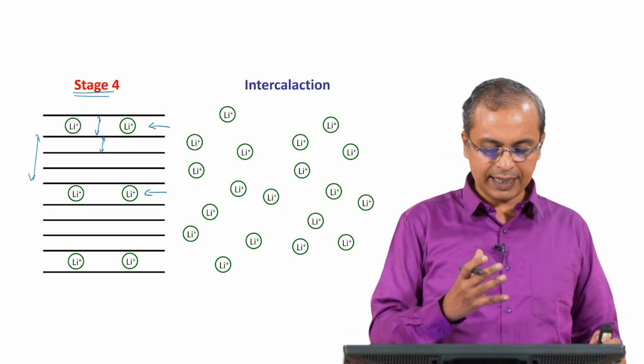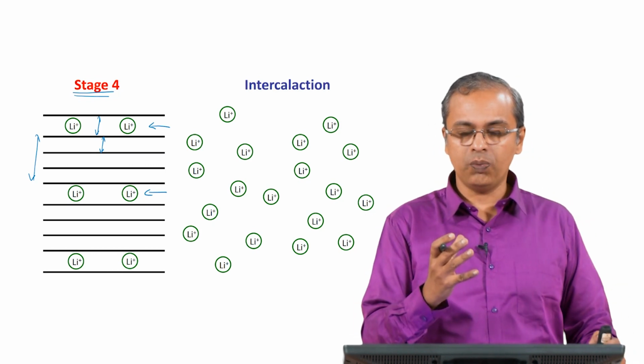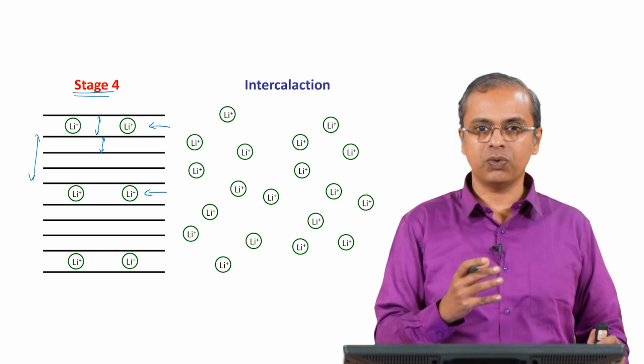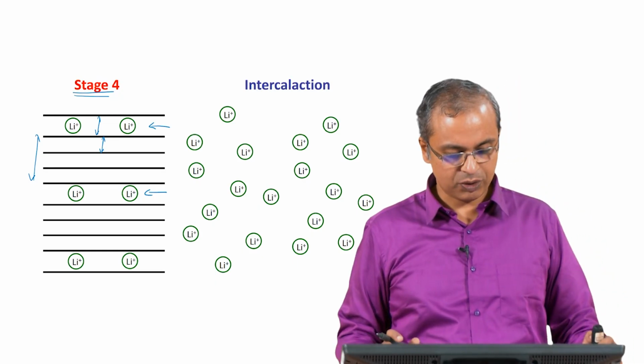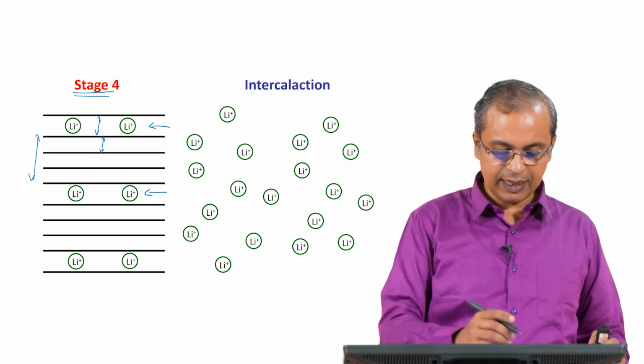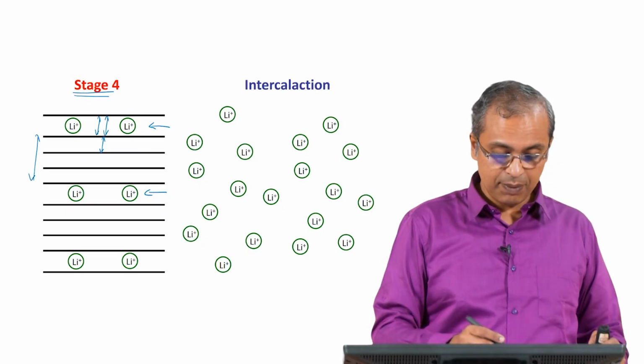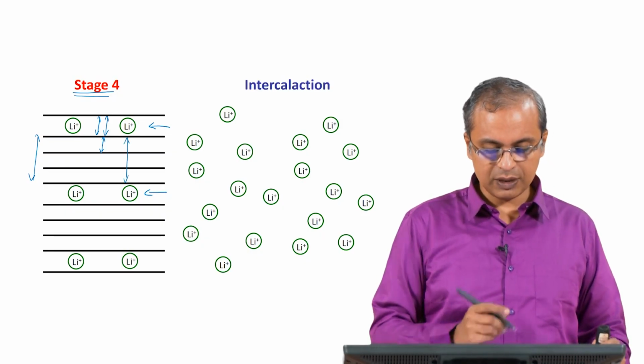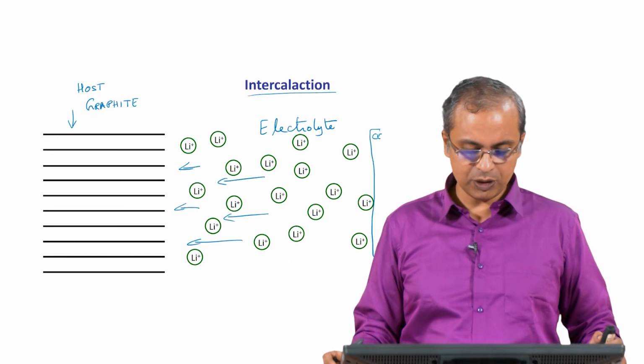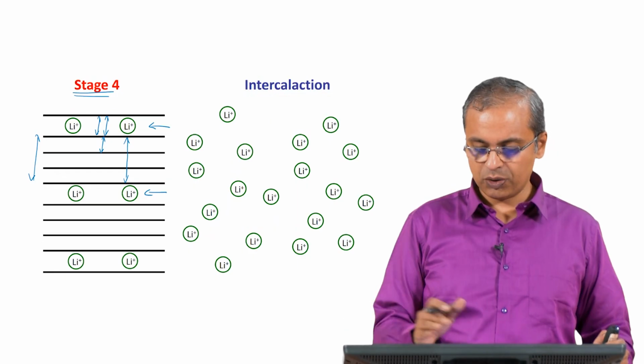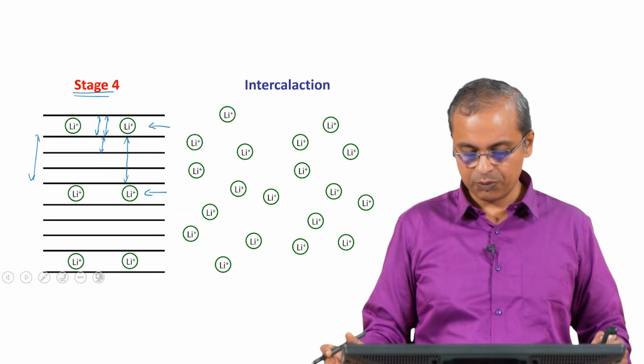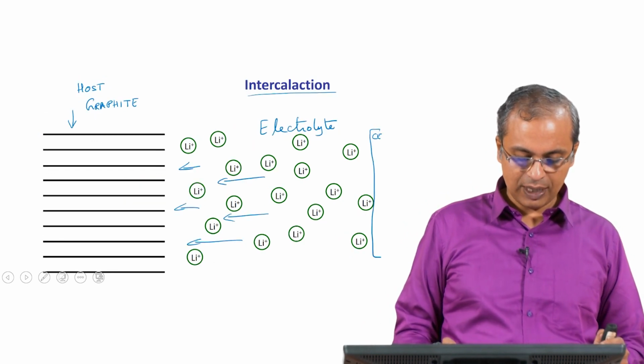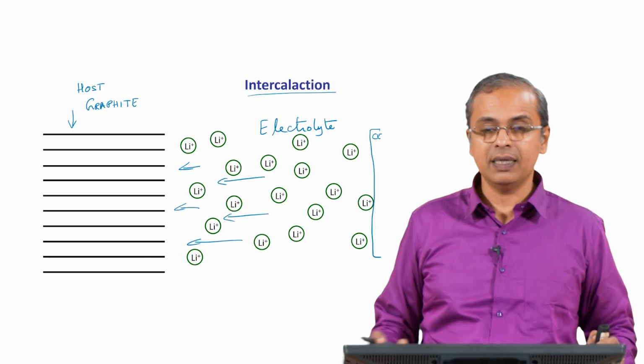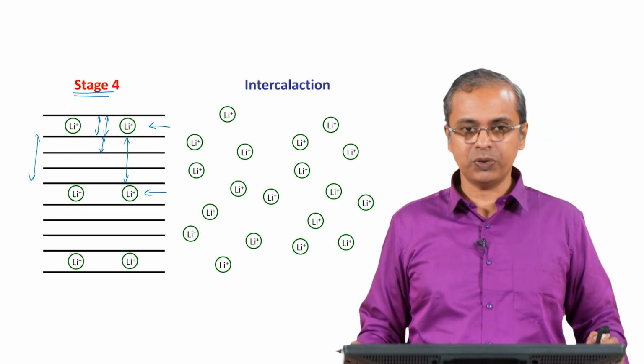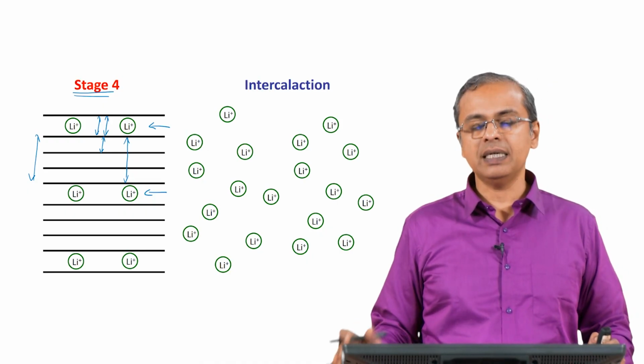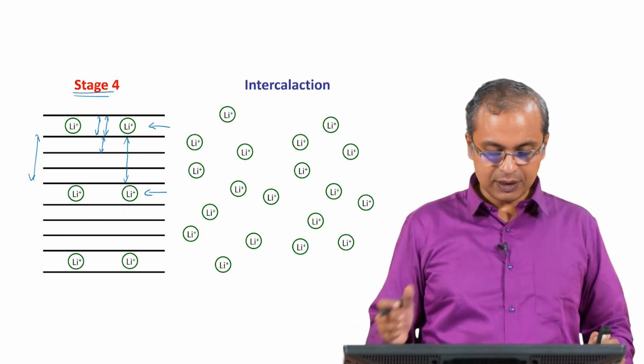There is a lot of study, and I know exactly what is the status of lithium there, how much of the electron is with it, how much of the electron is with the rest of the host material, etc. So for our purpose we will simply call it the lithium ion that is there. So the lithium ion has come in there, and then it has increased the spacing between graphene layers where it is present, but these spacings are undisturbed, right. So this is the original spacing. If you compare again with the previous picture, this is how our previous picture was, and you have some variation in the electrolyte also because ions are moving. So you can see the ions, if you look at the electrolyte side, ions are moving. If you look at the electrode side, the spacing has changed, you had uniformly spaced graphene layers, and you find now that some of the graphene layers have been pried apart, have been pushed apart, and some of them continue to remain as per their original spacing, and you have this lithium that has come inside it. So this is stage 4.